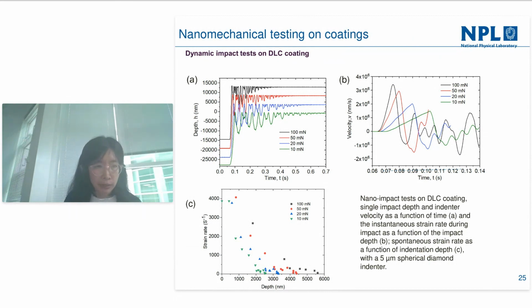Similar to the tungsten carbide, we have the depth data as a function of time, and in figure A is the depth profile at different acceleration loads. We then further calculated the velocity at the different acceleration loads. As you can see, the maximum velocity increases with the load, and we then calculated the instantaneous strain rate, and similar to the velocity, the strain rate increases with increasing acceleration load.